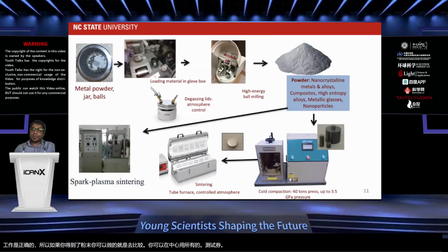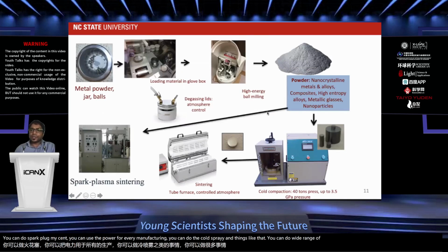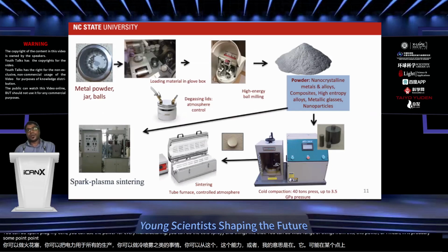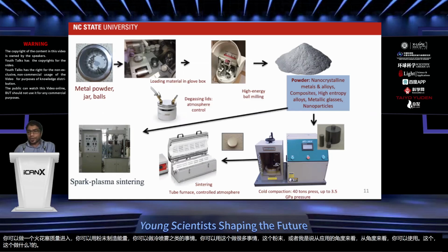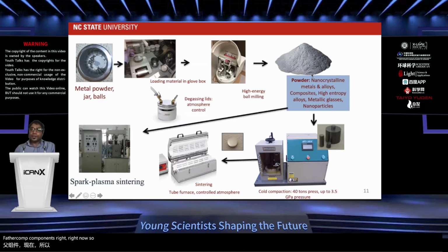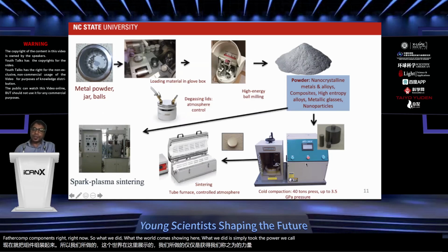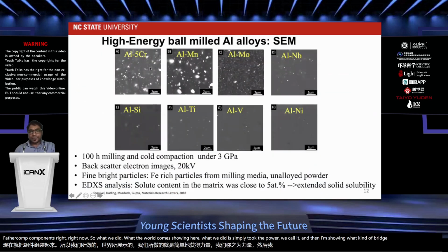You can do spark plasma sintering. You can use the powder for additive manufacturing. You can do cold spray and things like that. You can do a wide range of things from this powder. From an application point of view, you can use this to make powder metallurgical components, right? So in the work I'm showing here, we simply took the powder, cold compacted it, and I'm showing what kind of result we get.